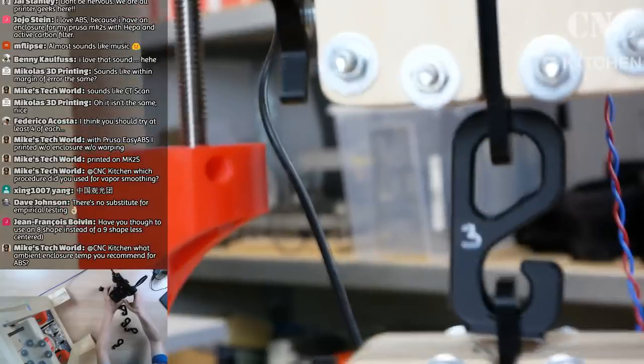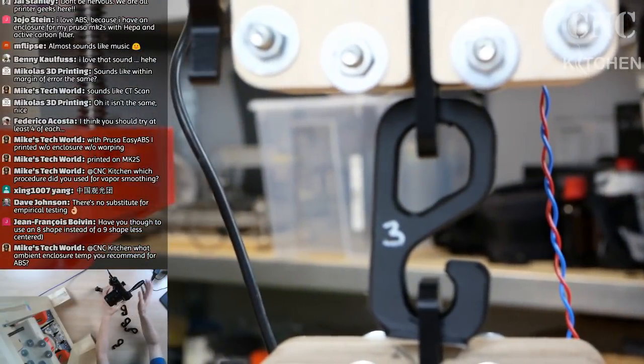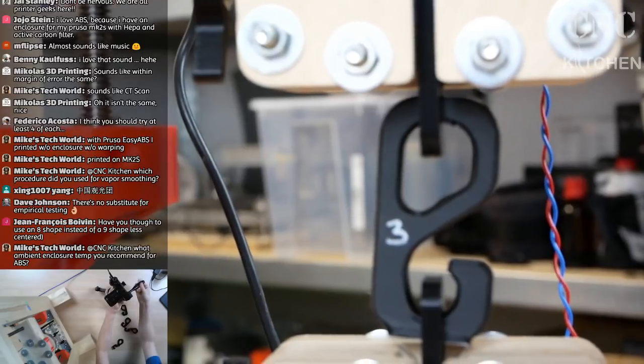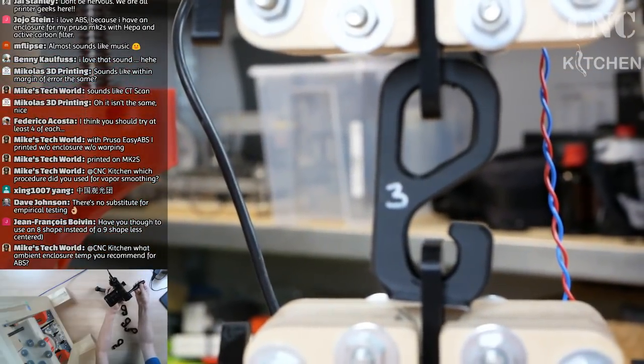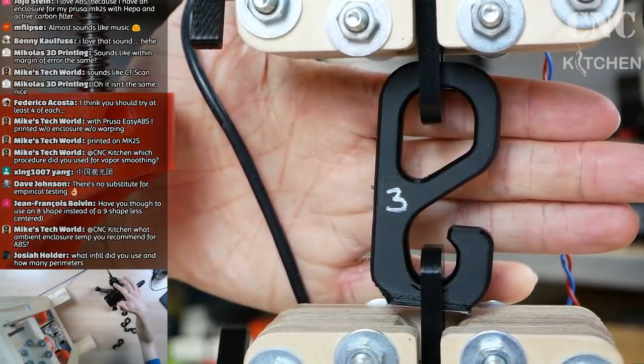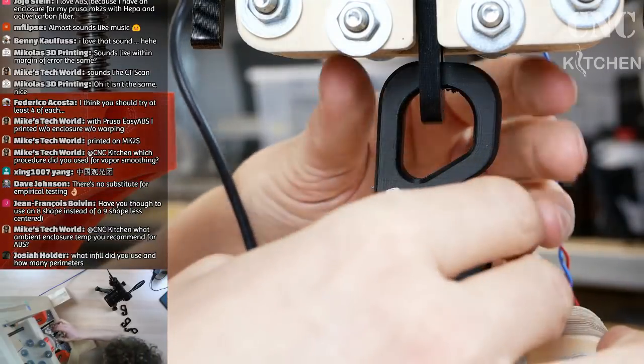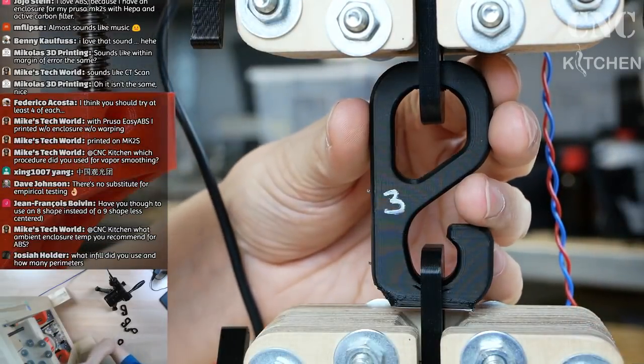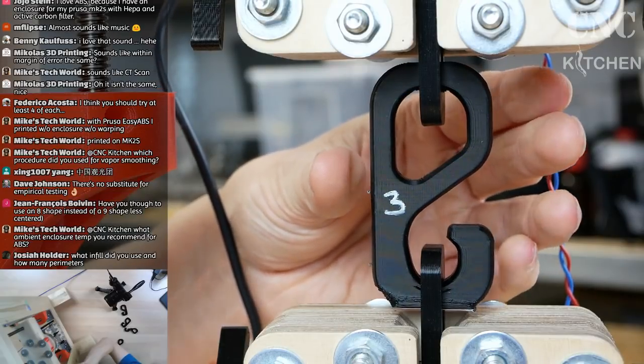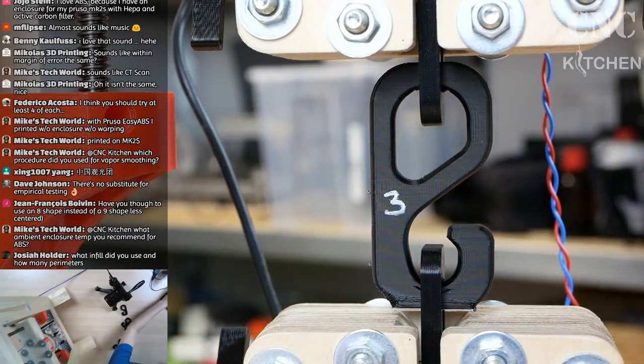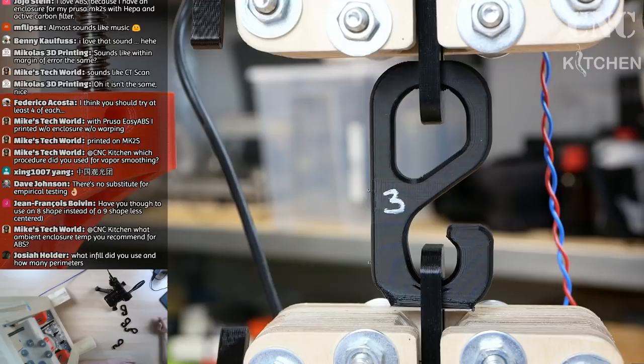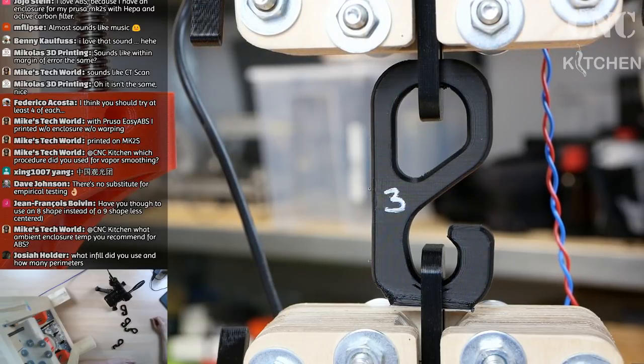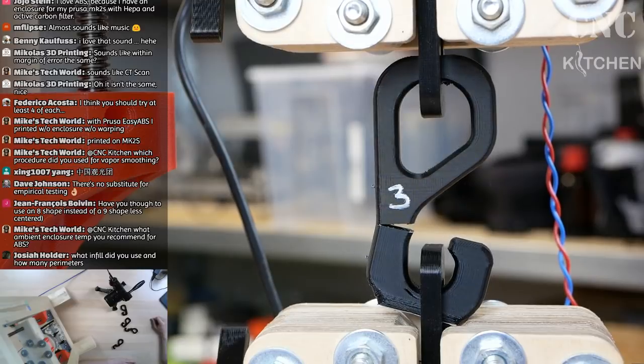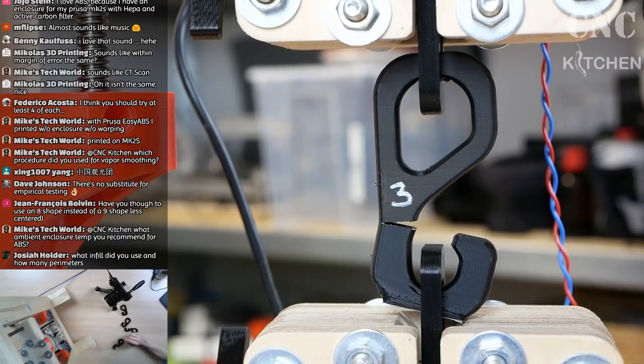Maybe I move the camera a little closer to the specimen so that we might be able to see the failure better, which I'm quite sure will happen much earlier than with the last one, because this is just testing the layer adhesion of the part. Wait a second. All right, so we are at 0, and let's start the test. Okay, 10, 20, 30, 40, 50, 60, 70, 80, 100, 130, and we are done.